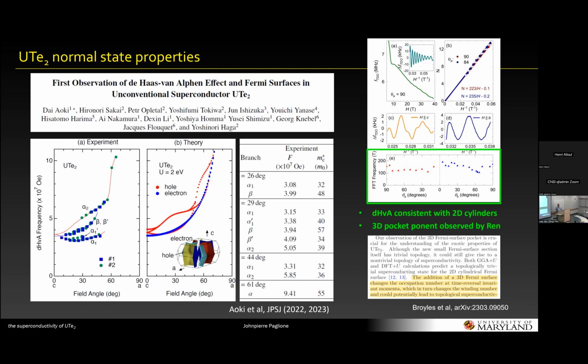But it's a Kondo effect, so there's going to be a hybridization. But they have to be close to the Fermi surface to hybridize. Yeah, they can be close, but not cutting the Fermi surface. As you know, when you do DFT with F states, you usually just get a flat band that you can push away, even with any rare earth, for instance. So the band structure I showed is probably a thorium tellurium 2 band structure, a hypothetical band structure with no F's. Right, it depends on what kind of DFT they did. If they put it into the core, then the F's are gone from the beginning, right?